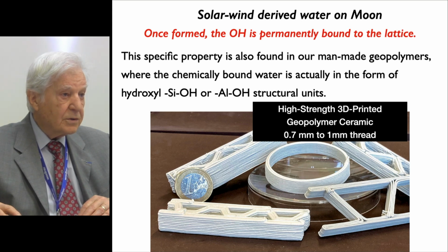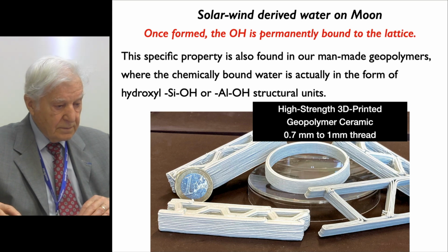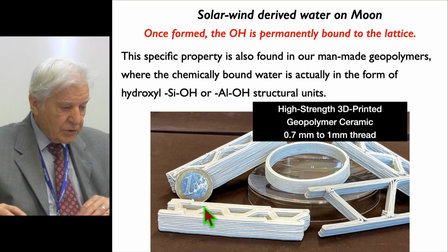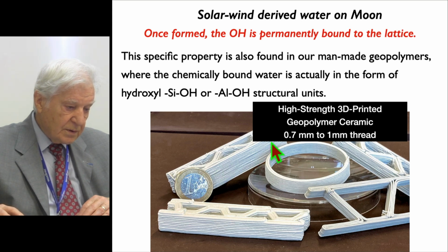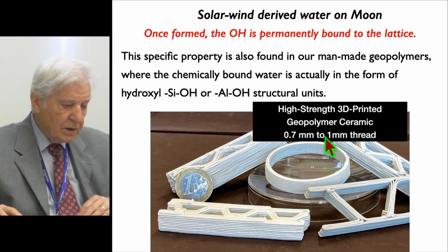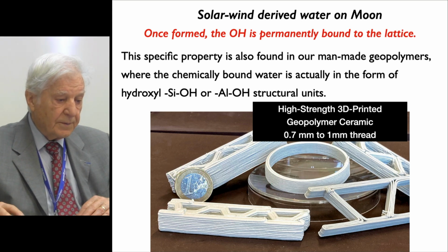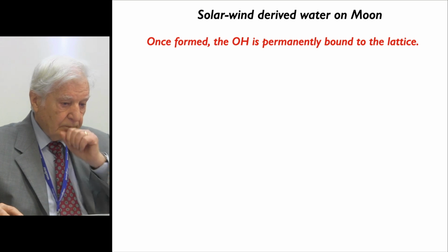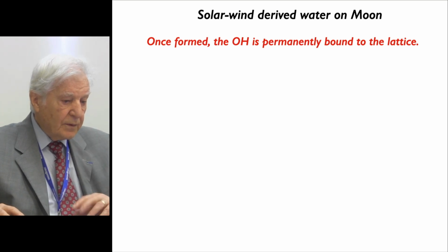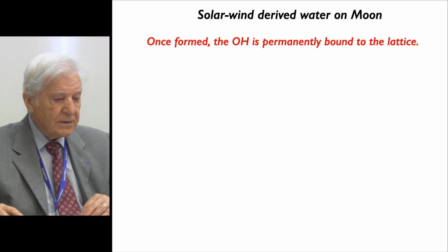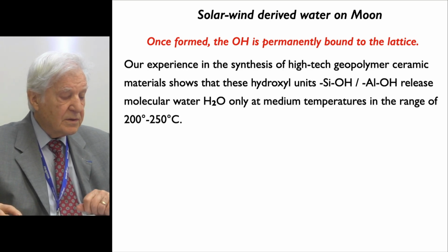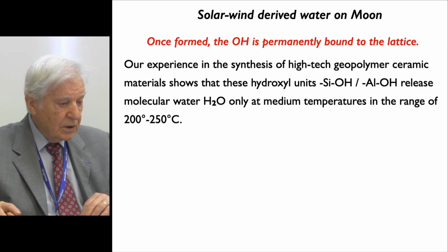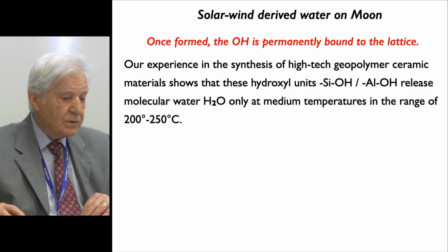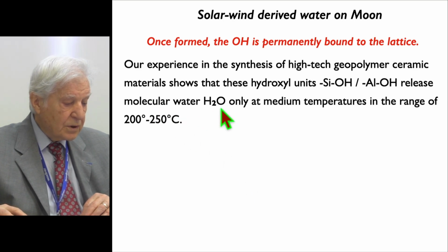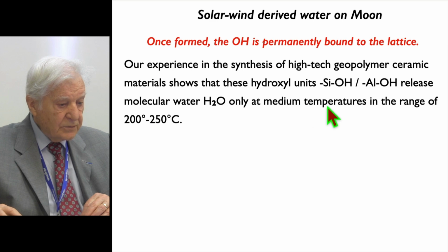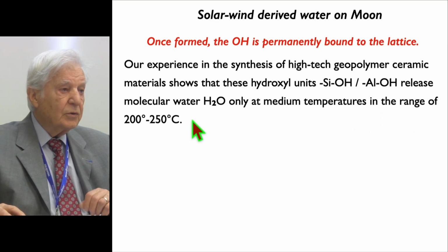We used our geopolymers to produce ceramic type material, and you see the dimensions of the materials, 0.7 millimeters of the thread or 1 millimeter compared to €1 coin. Our experience in the synthesis of high-tech geopolymer ceramic materials shows that these hydroxyl units, SiOH, ALOH, release molecular water, H2O, only at medium temperatures in the range of 200 to 250 degrees C.